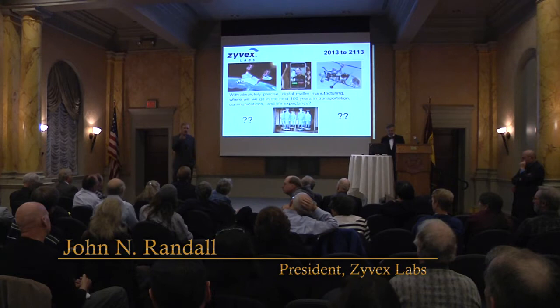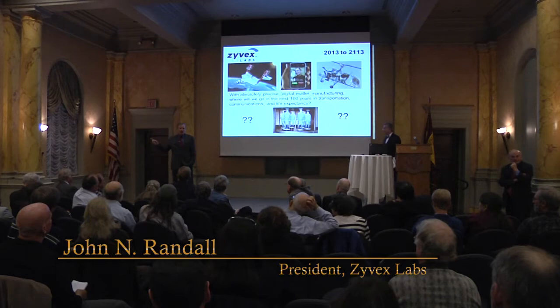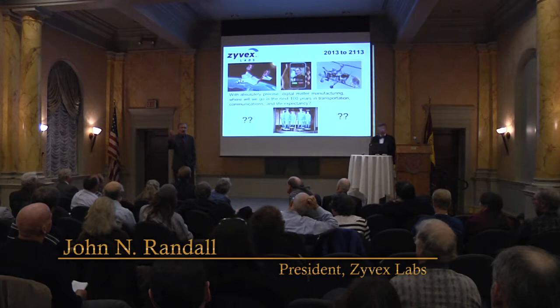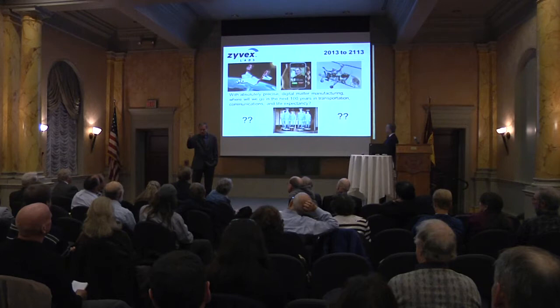And by the way, somebody asked me a question about how long that I didn't answer, about the speed. Let me try to answer that and answer you at the same time. Currently, we can remove about 100 hydrogen atoms a second, with the low resolution, the high resolution mode. At the high biases, we can remove orders of magnitude more than that. We can do a square micron in a relatively short period of time, whereas with a little single tip, there's a lot of atoms in a square micron of silicon.